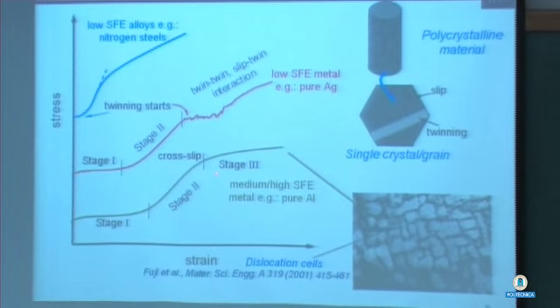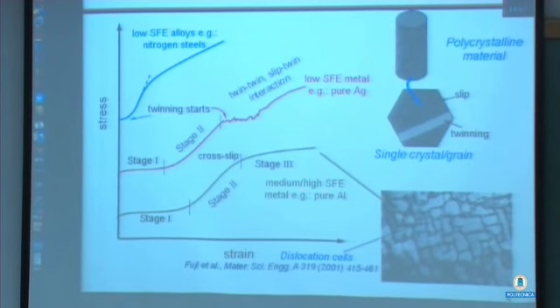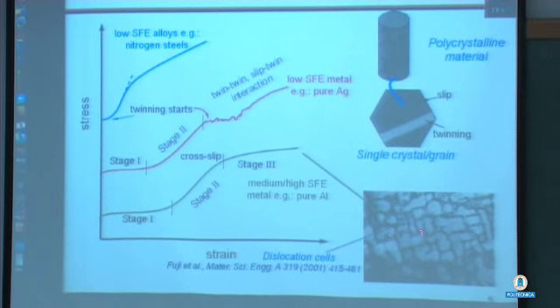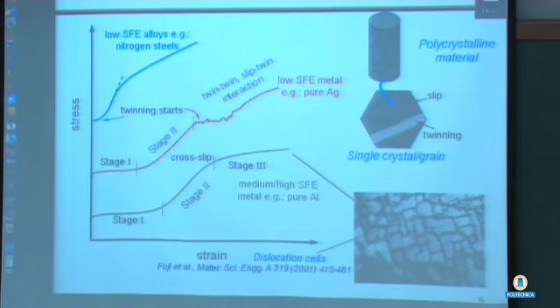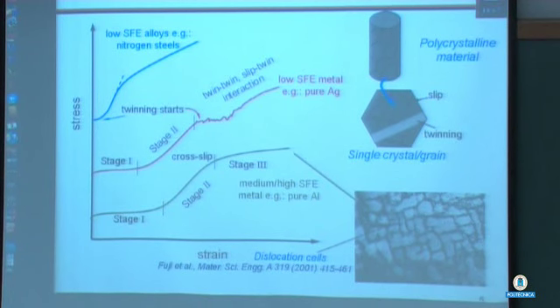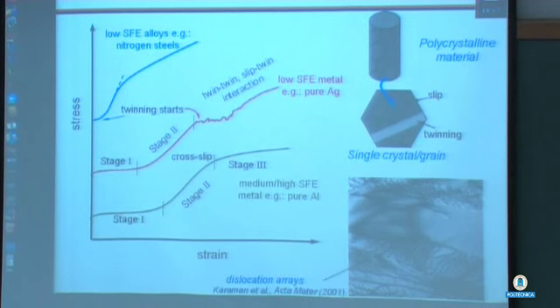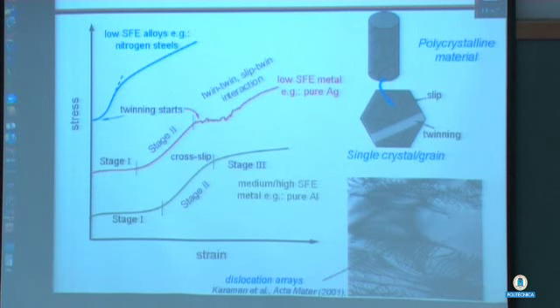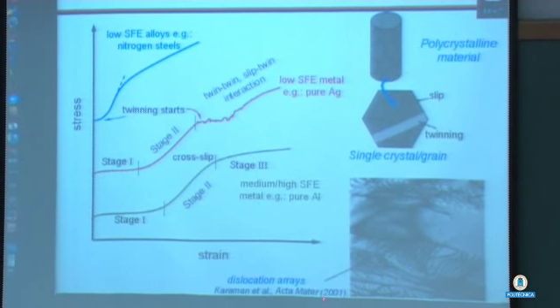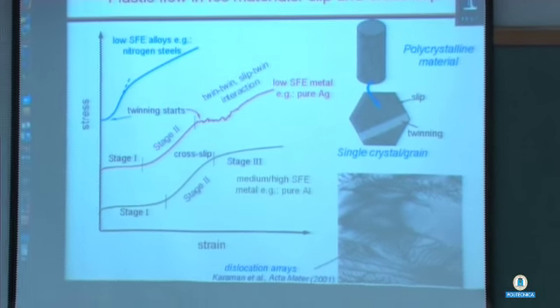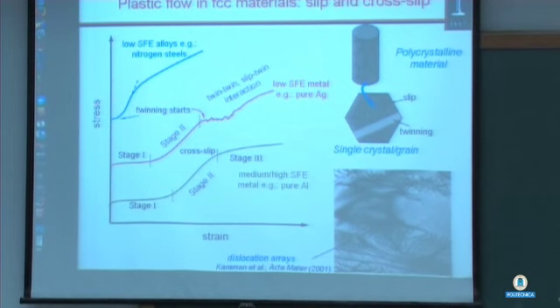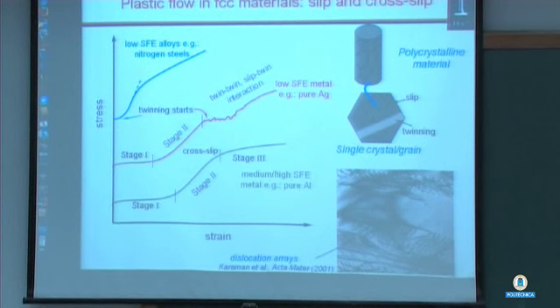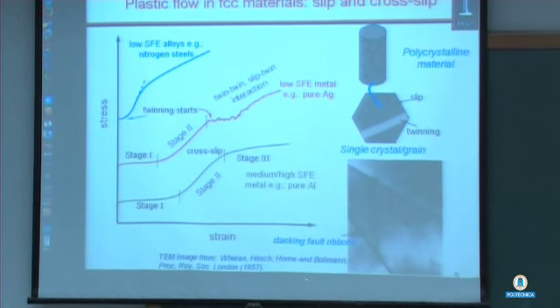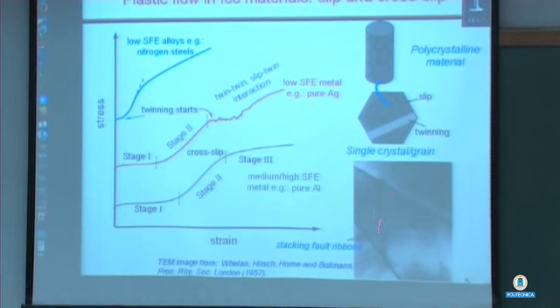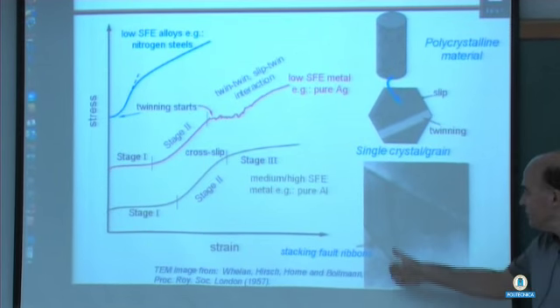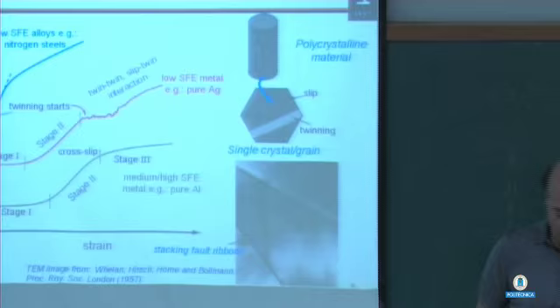Typically in materials that do not twin, in medium to high stacking fault energy materials, you get dislocation cells because things can cross slip and you form these three-dimensional structures. In materials that are low stacking fault, you get more planar structures, and that would be this material, the red one, or the blue one, for example. This is again the ones with low stacking fault energy materials. These are stacking faults.